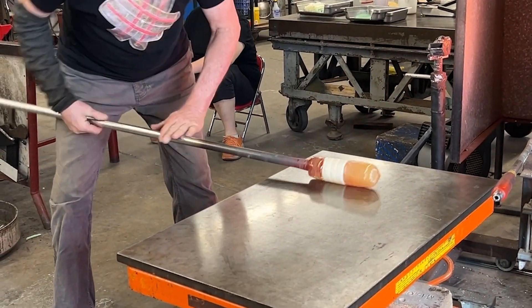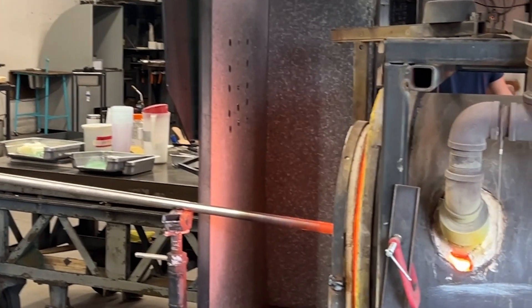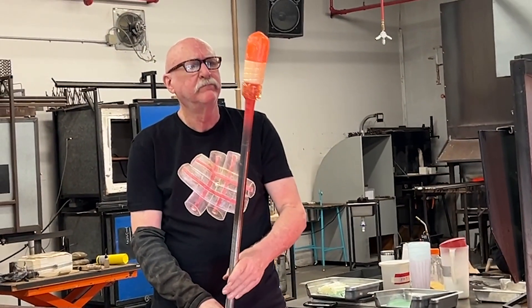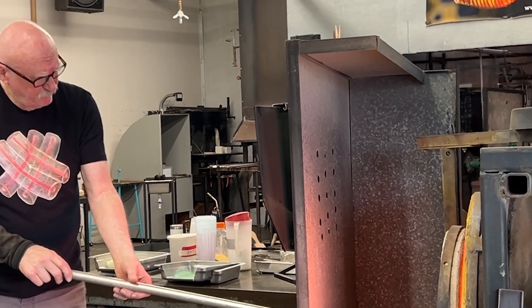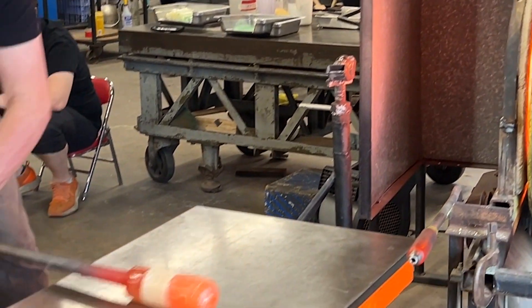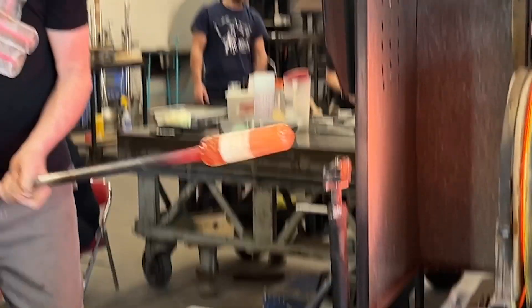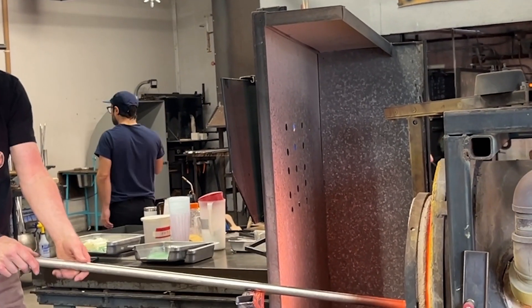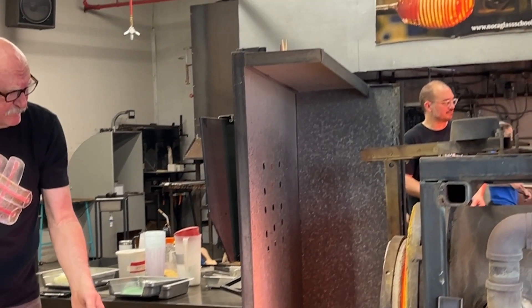What he's rolling on here is called a marver. These were originally made out of marble, and that's how you cool and shape it. Even if there are creases in it, when he goes to gather more glass, that will trap bubbles — but he doesn't want bubbles trapped in it. They do use gravity; in the later process of making the vase, he will swing things out, blow the bubble up, and then swing it to allow gravity to elongate it. That's about having enough heat in it so the glass is still soft.